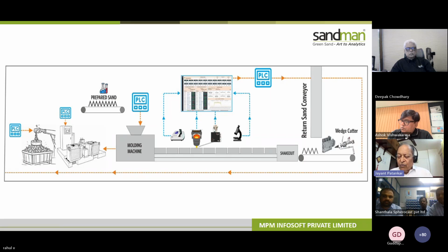But if you have to add more and more for any commercial reason or a management decision, then you have to calculate and add those elements which are going to burn away in the furnace itself. So in the initial stage, the cost of basic scrap and the cost of the borings will be factors you have to take into consideration. You can't use any amount because of the constraint, but for a good casting and consistent output, I would recommend a 20% cap on the charge calculation.